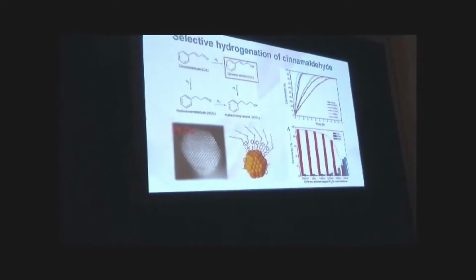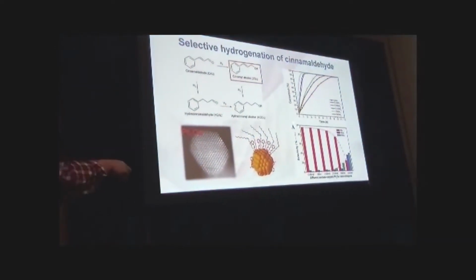When you use the catalyst with organic modification, because the organic ligand blocks some active sites, the reactivity is very low, but the selectivity is very high. We can replace the long-chain amine with short-chain amines, such as C12 amine, C8 amine, and C4 amine. The reactivity increased, but the selectivity decreased.